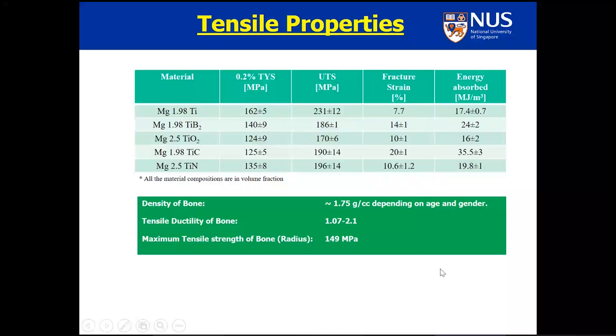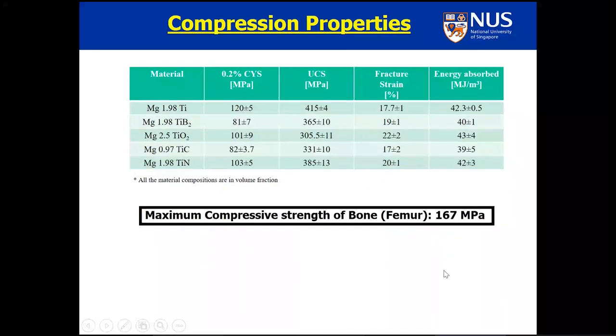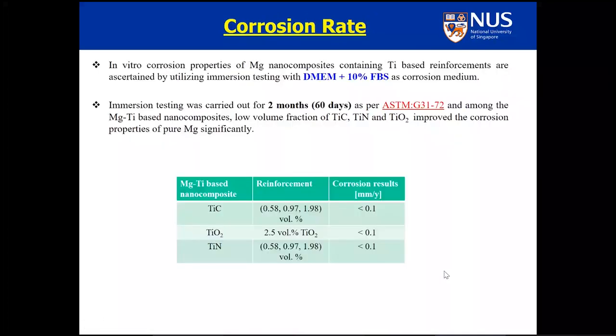So these are the mechanical properties. But when you put it in the body, it's the biomechanical properties. So we have to do the corrosion testing in the physiological medium. There are many of them. And when we talk with the surgeon, they say that the corrosion rate has to be less than 0.2 millimeter per year. And all these things that we use show a corrosion rate of less than 0.1 millimeter per year, which is acceptable.